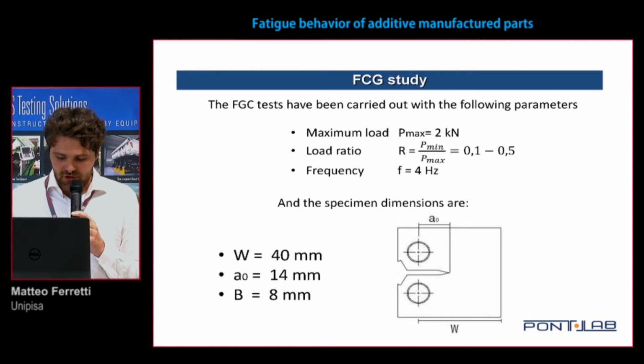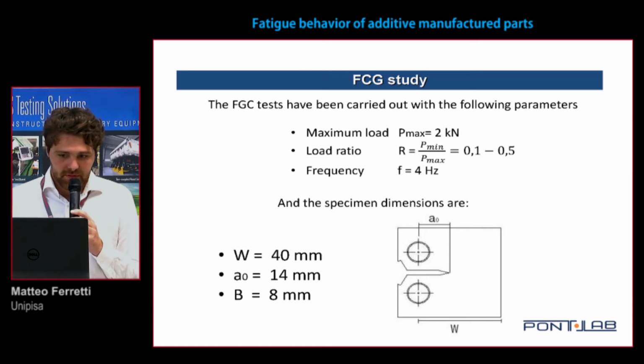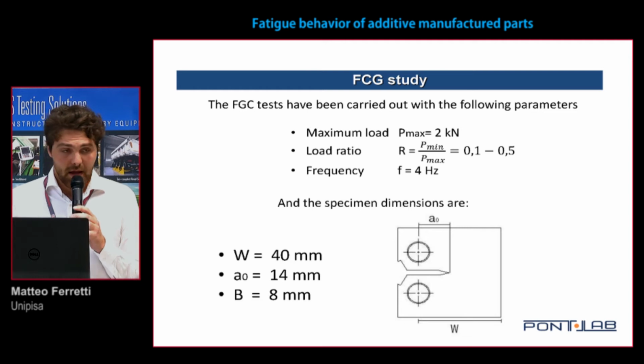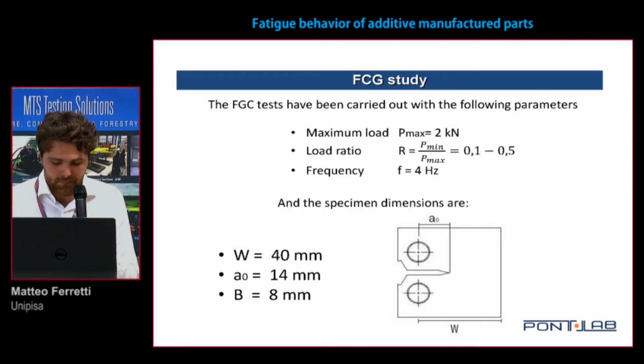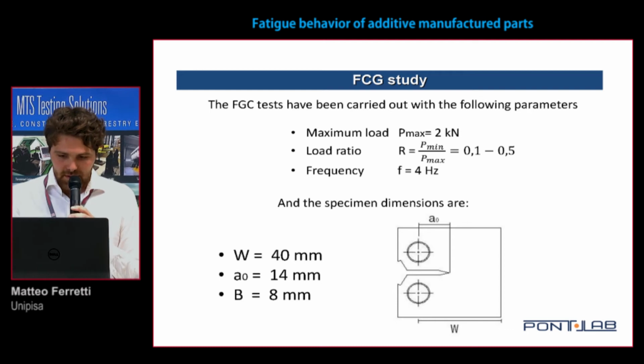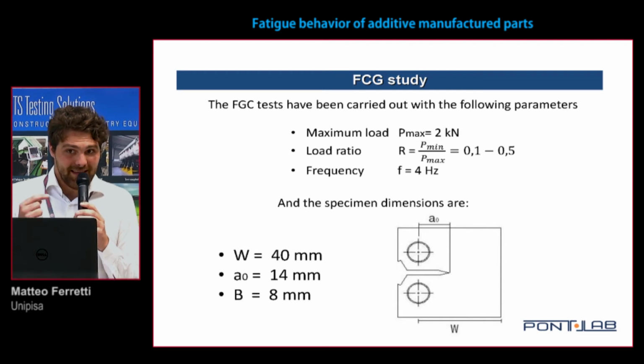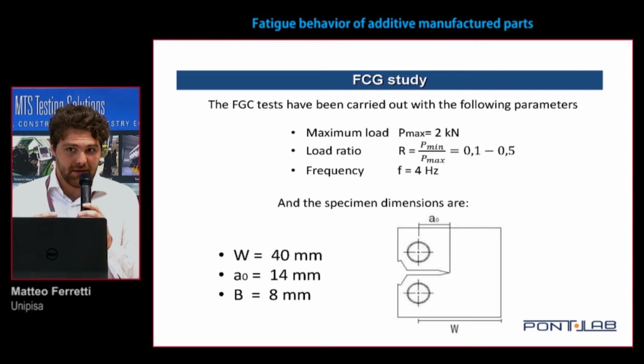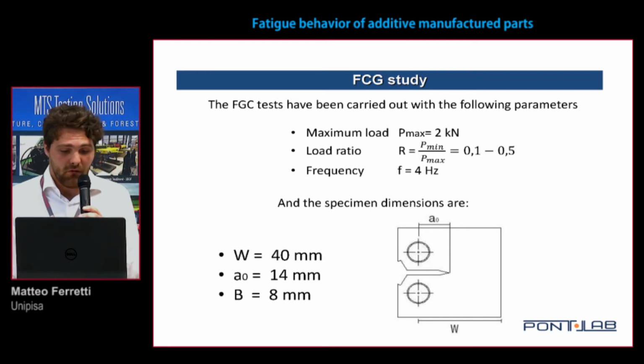The FCG test have been carried out with these parameters: maximum load and amplitude of 2 kilonewton, load ratio, that is minimum load over maximum load, equal to 0.1 or 0.5, and a frequency of 4 Hz. The specimen that is like this in the picture is CT specimen, compact tension specimen, and the dimensions are the following: W of 40 millimeters, A0 of 14 millimeters. A0 is the initial notch for the crack, the cracking of the specimen, and a thickness B equal to 8 millimeters.